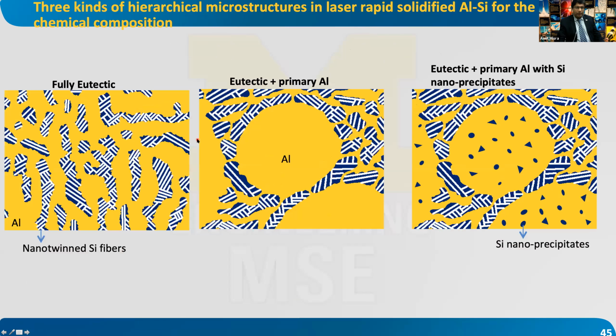So just to summarize, from the same composition, that's the key point. We did not change composition. There's maybe a subtle change in the cooling rate in terms of where we saw the structure with respect to the free surface. Maybe some of these are forming at a higher cooling rate than the other, but this is very different from the regular eutectic structure that you will form under melting. This is different in many ways.